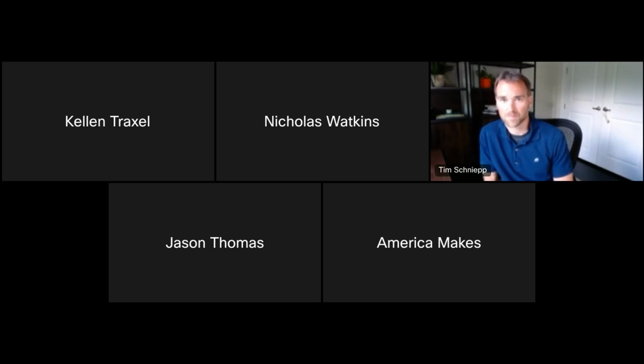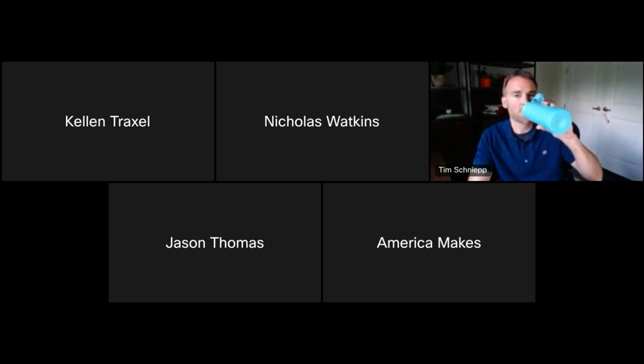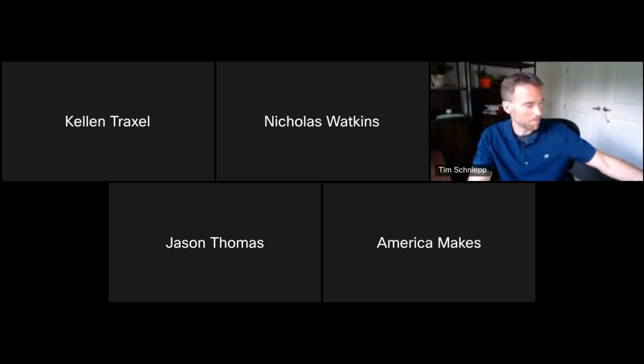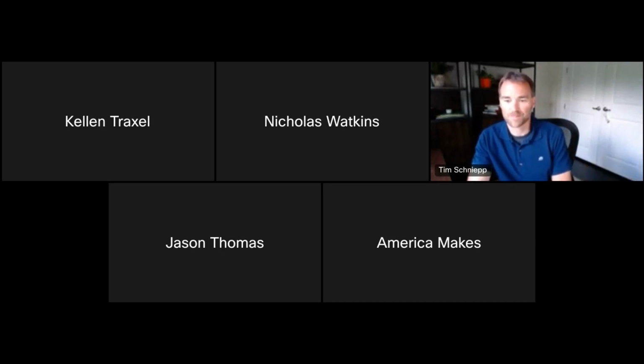Obviously, the resolution is a challenge right now because we're working with 500 micron drops. So we see about 1 millimeter line thickness, because if your build plate temperature is hot enough, the drop will come down like a pancake versus a spherical drop, if it wets the surface, of course. So I think resolution is the biggest challenge, and then the material selection right now. And as Tim said, there are a lot of material science questions, a lot of complicated components in the head that make going up in temp challenging. So that's kind of my take. I don't know if Nick maybe has something to add to that.